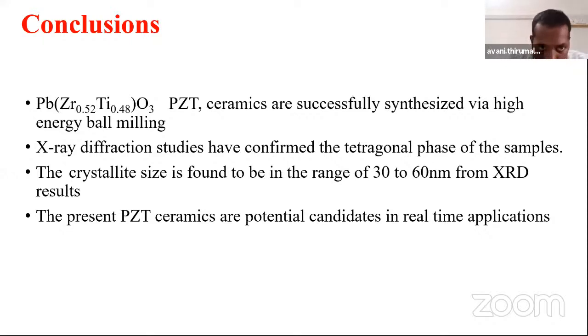These are the conclusions. The piezoelectric materials are successfully synthesized by high energy ball milling. I am focusing on high energy ball milling. So many wet routes are also there, but they won't give a good yield. For that, I am choosing ball milling. X-ray diffraction confirms the tetragonal pure phase, and the crystallite size is nearly 30 to 60 nanometers. Finally, the present PZT ceramic materials are applicable for real-time applications.